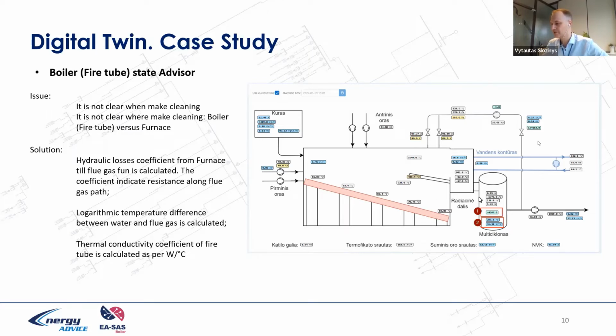From the furnace side till the flue gas fan, the hydraulic losses coefficient of the flue gas route is calculated, and this coefficient indicates resistance along the flue gas path. Another coefficient is the logarithmic temperature difference between the water side and the flue gas side, and the thermal conductivity coefficient from the fire to the water side of the fire tube is calculated in watts per Kelvin.